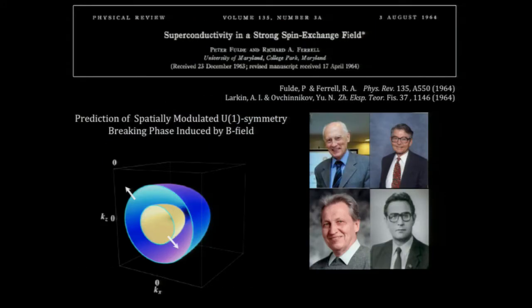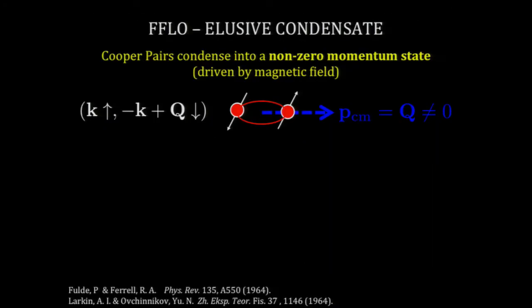And this really goes back to the 1960s. This idea was first proposed by Fulde, Ferrell, Larkin, and Ovchinnikov, who said, what if you took a superconductor and you put it in a very strong magnetic field, such that you split the Fermi surface between the up and the down states. So usually we have up and down at equal energies pairing to make Cooper pairs. But if you now lift one Fermi surface relative to the other one, you can't pair minus k and k to make that Cooper pair anymore. Now you have to make some different kind of states. And in that scenario, you take a k in the up state, and you take a minus k plus q in the down state, and those are the ones that can pair. And then in contrast to regular Cooper pairs, this Cooper pair has a center of mass momentum which is no longer 0. It actually has some non-zero value, which is equal to q.